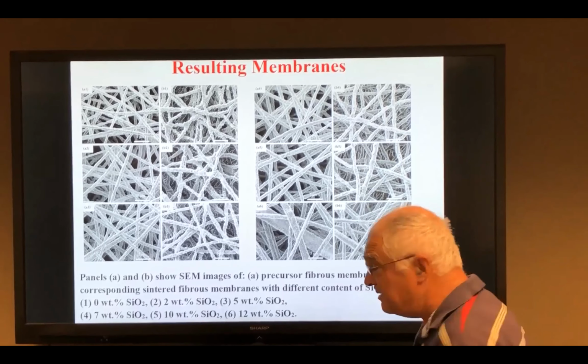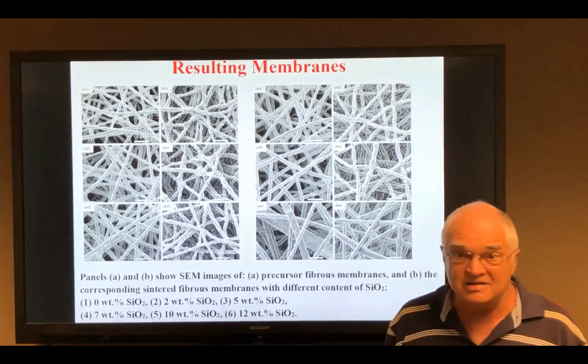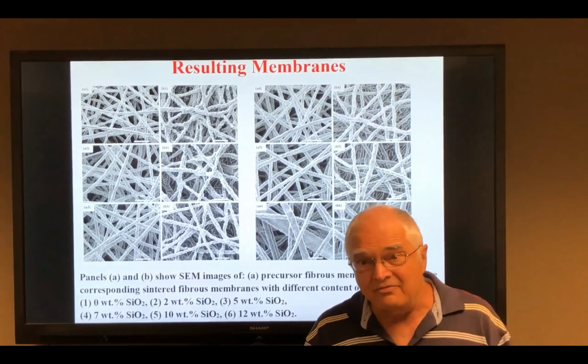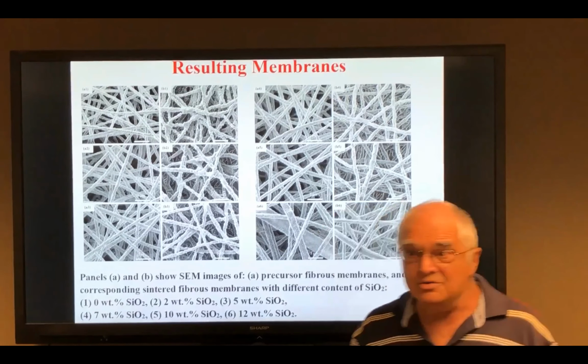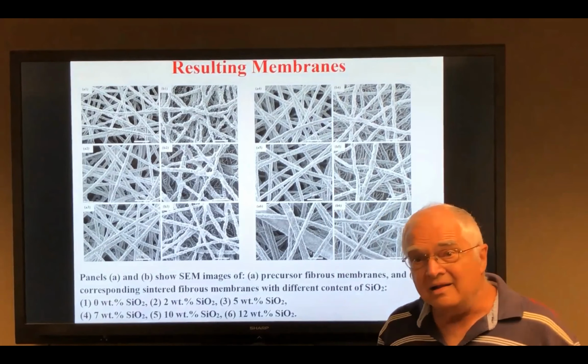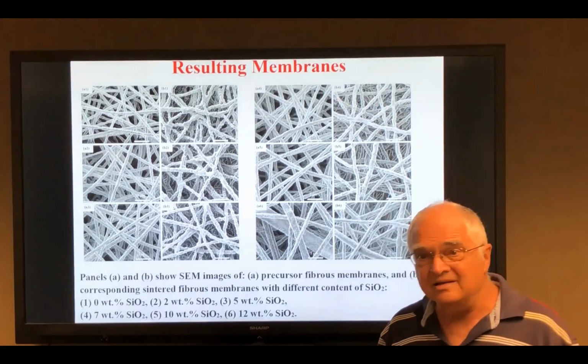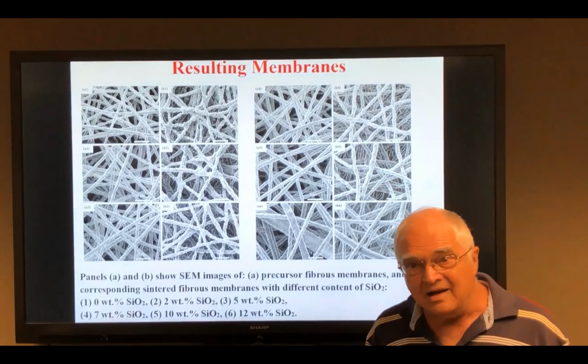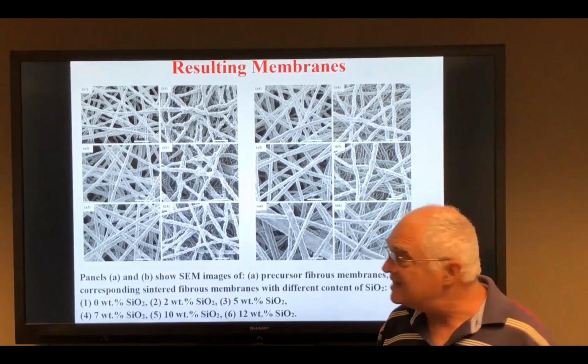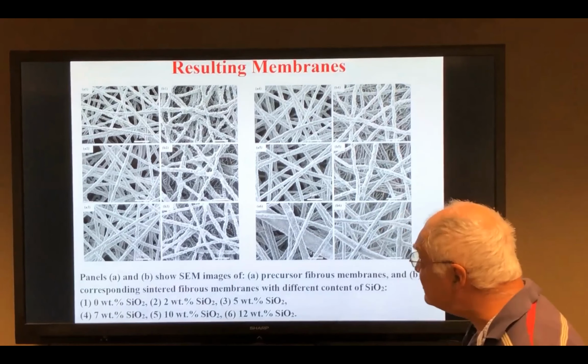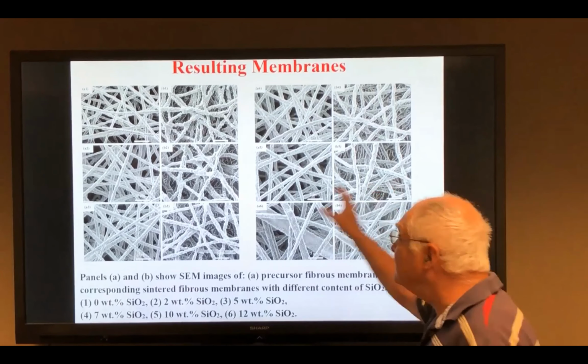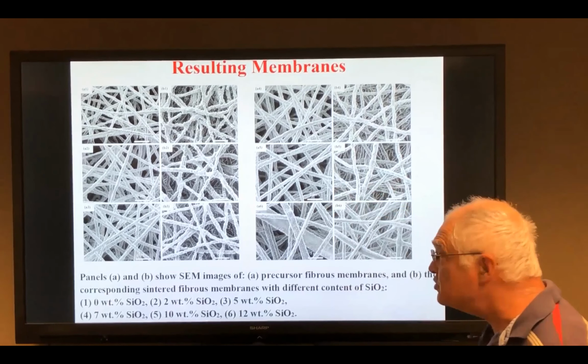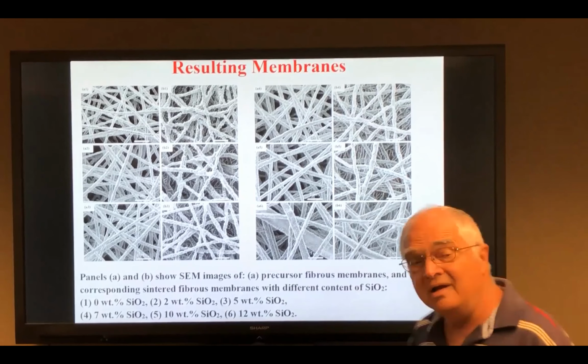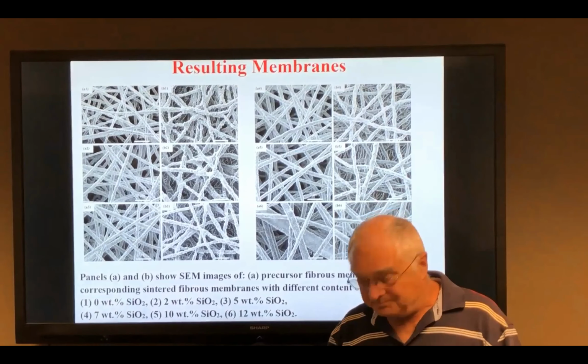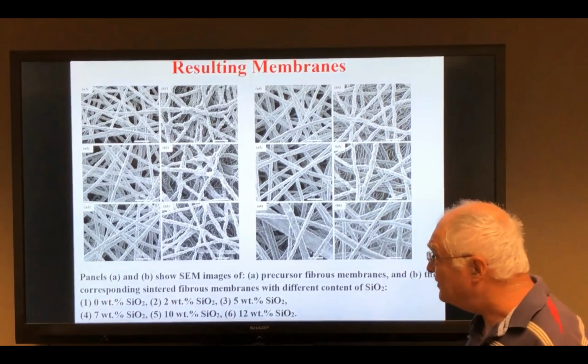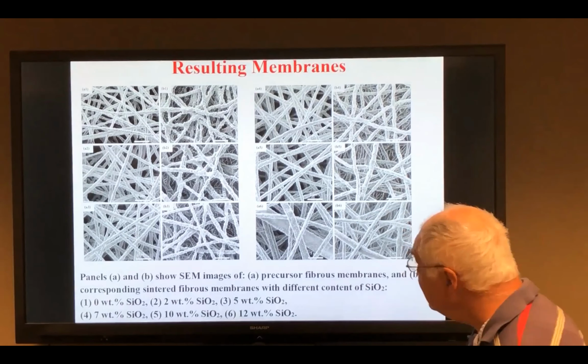best composition. By the way, these compositions are judged not only by the fibrous structure, but also by durability in abrasive tests and waterproofness in dripping test, as well as in self-cleaning. So all these different compositions should be tested, and a trade-off should be found, and that would be the best composition. So please go ahead.